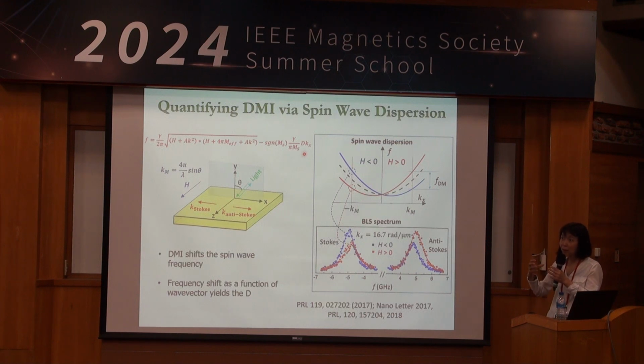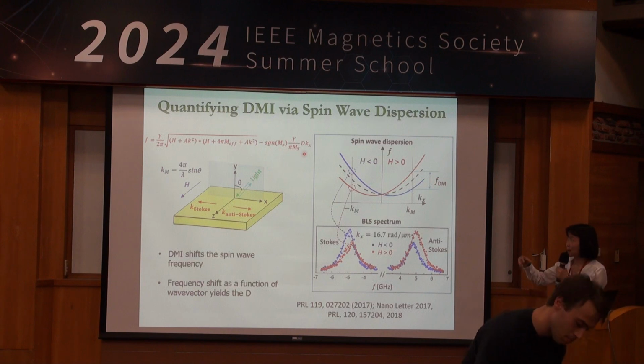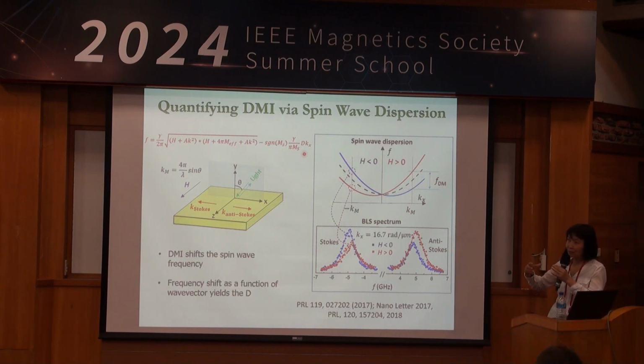When you have a constrained geometry, where you have losses, over the length scale of 10 nanometers, the momentum conservation is out. So this language is approximate. And then the wavelengths of the magnon I pick up are oftentimes constrained by the geometry of the device I'm measuring, no longer by the photon momentum.